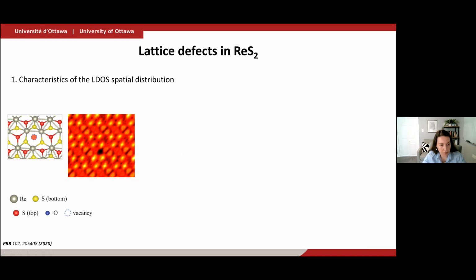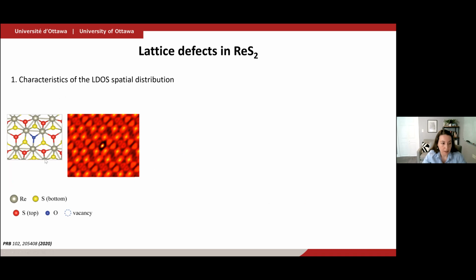And then they're able to help us by simulating the local spatial distribution if you, for example, remove a sulfur atom, which you might think is the most common type of defect in these 2D materials. However, removing a sulfur atom does not resemble what we see in experiments. And then the idea is, well, can you have an oxygen that was grabbed by this defect from the atmosphere onto the vacancy? And indeed, that starts to look more like what we see in the experiment.